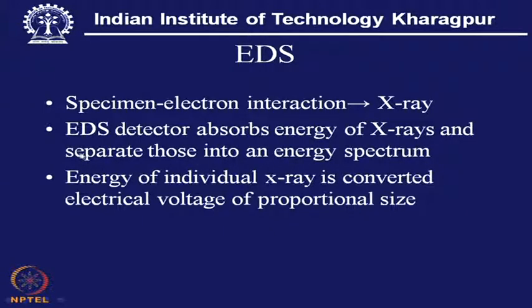So, this is very important, it should be able to separate. And finally, what happens is that the energy of an individual X-ray is converted into an electrical voltage of proportional size. So, this electrical voltage, this X-ray, is typical characteristic of one individual element. So, from that it is possible to find out the element which is present, what is the percentage, and also the combination, that means the percentage of element and also the atomic ratio, in what atomic ratio it is present in that volume.